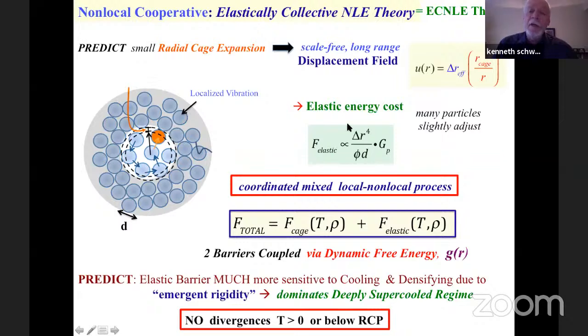And it can be numerically and analytically shown that this elastic barrier scales as 4 powers of the microscopic jump distance and 1 power of the dynamic elastic shear modulus. So the physical picture then is of a coordinated mixed local non-local process, which is what the alpha process is. And the barrier has a local part and a non-local part, but they're intimately coupled because everything that determines them comes from the dynamic free energy and hence g(r).